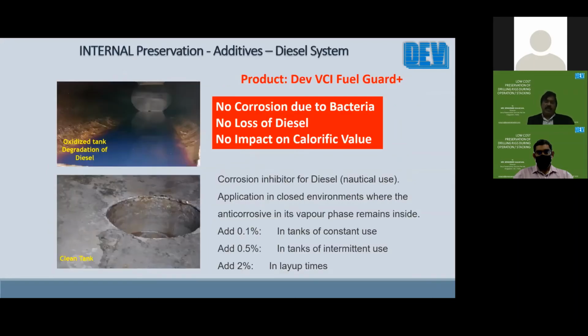And this is the photo above. It shows the condition of a diesel tank after about 4 months of leaving it with diesel inside after the pre-commissioning phase. During that period, sulfate-reducing bacteria damaged the diesel quality, and also caused corrosion and bacterial growth inside the diesel tank, for which a fuel guard solution is available.